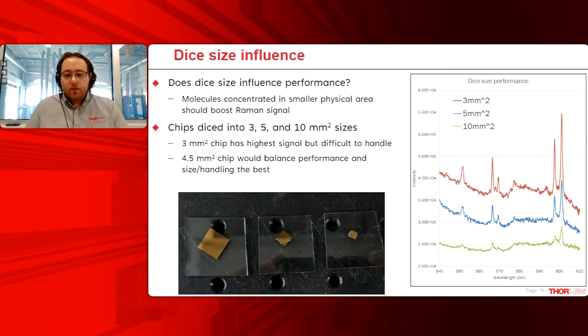So we diced some different sized chips, and we found that, in fact, the 3 mm squared chips did have the best performance. However, we found that 3 mm squared chips were surprisingly difficult to handle. They would often slip out of your tweezers and move around on your stage because they're so small. So we decided that 4.5 mm squared was a really nice balance between performance and handling for the size of these substrates.